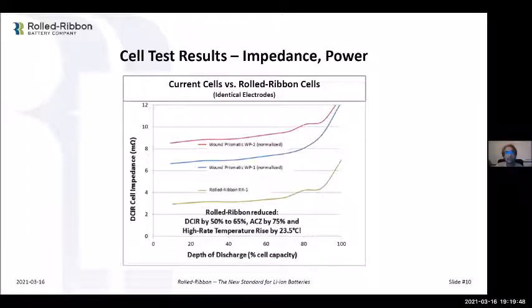Okay, on thermal issues, is there any kind of failure mode that might lead to runaway or thermal runaway? Yeah, so there's several things. We will do better in thermal runaway for any given electrochemistry, because our package design allows you to extract heat faster than anybody else. What drives thermal runaway is that heat builds up until you reach the runaway point, and then it's like an avalanche. The biggest component of thermal runaway, the baseline that you work from, has more to do with the safety of the electrochemistry than anything else. Then you get into the thermal properties. And like I say, our thermal resistance is so low, you can get the heat out faster. So it makes it harder for the cell to escalate the temperature.